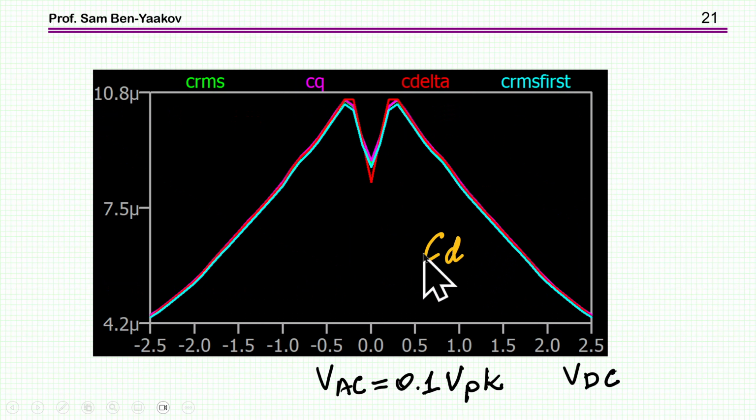And having this high resolution model, I can now run it with a very fine excitation of only 0.1 volt peak, rather than the 0.5. This is the RMS, but this is 0.1 volt. So it's very fine resolution. And what we see here is that the CD is really changing quite a bit around zero. This is a double-sided simulation, just to show that plus and minus voltages are providing the same results, of course. And you see this hump here, and then you have this drop.